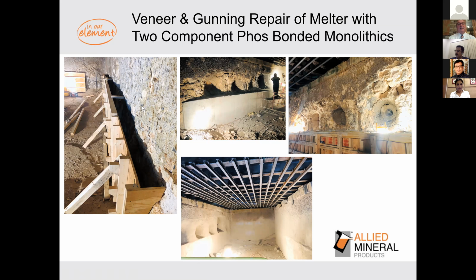But as you're always up against production, they're wanting the furnaces back quickly. So the customer still veneer casts from time to time, but they really have gone to just gunning our phosphoric bonded materials. And that will add about 18 months extension of life. It's not as good as veneer casting, because there you're vibrating versus gunning. But the colloidal silica would last about 9 months to a year. The phosphoric bonded gun mix would last 18 months, and veneer 3 years.